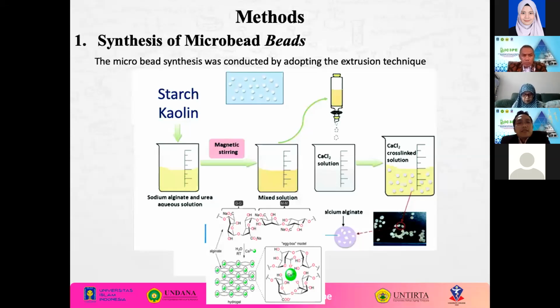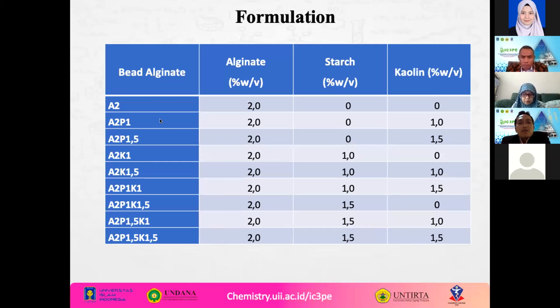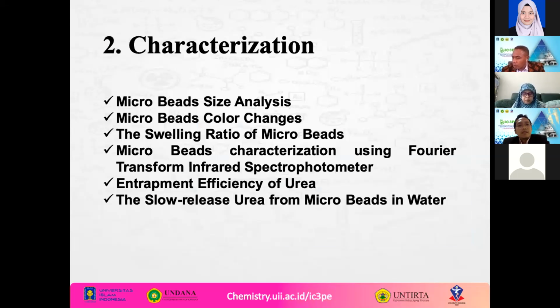For the method, in the synthesis of microbeads, we use an extrusion technique. The sodium alginate and urea in aqueous solution are added with starch, kaolin, or starch and kaolin, then the mixed solution is dropped into calcium chloride as a cross-linker, producing the alginate beads. And this is our formulation: A is alginate, P is starch, and K is kaolin. So we modify the variation of alginate, starch, and kaolin. And this is the characterization process, and this is the result. The photograph of the synthesis with alginate, starch, and kaolin beads.